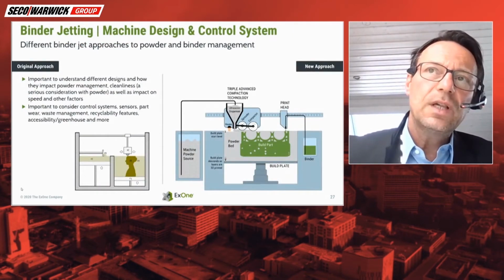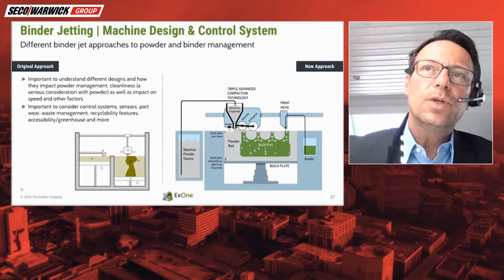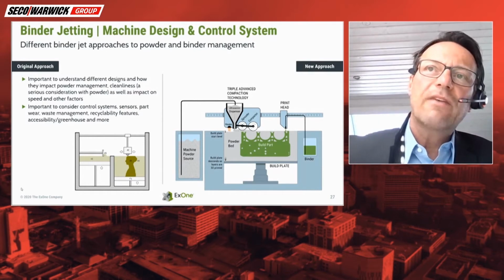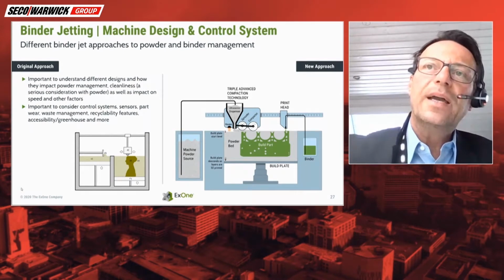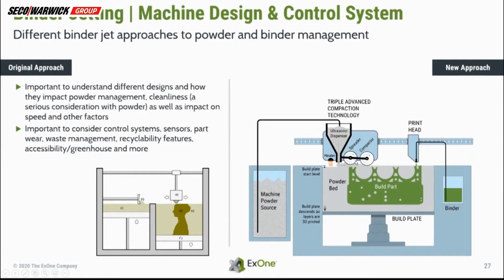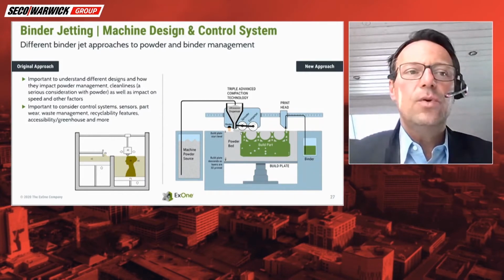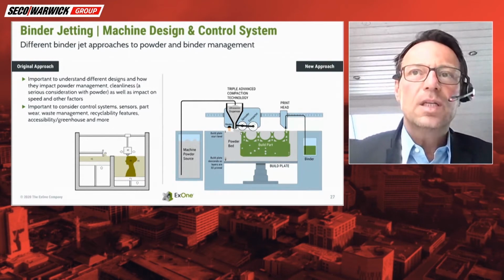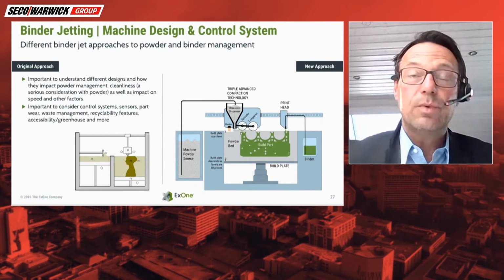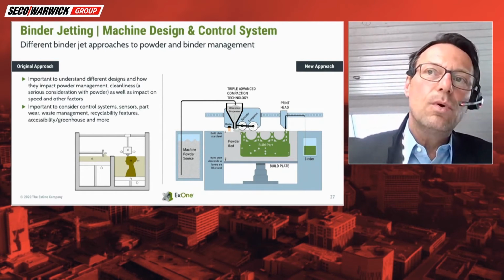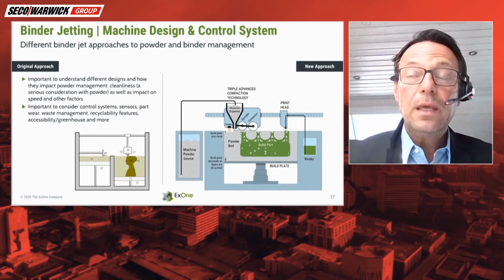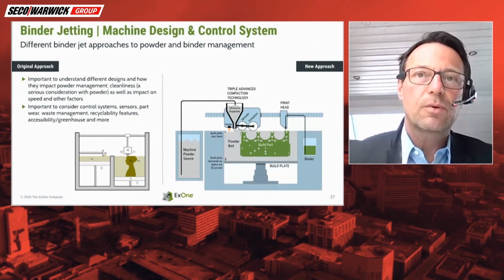Here you see a little more in detail how the ACT works. The advanced compaction technology: we have this ultrasonic hopper, and the powder is dispersed through the hopper, then we have two rollers which are leveling out and compacting the layer we put on top of the other layer, powder layer by layer. It's a very constant and very homogeneous way of spreading out and recoating the powder, which is important if you consider that at the end we will build a part which has to go through a different process, which is the sintering process. The more stable and more homogeneous the green part is, the better the result is going to be after the sintering process.